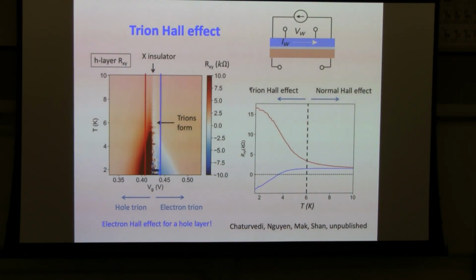Yeah. Trions are fermions. Yes. Unfortunately, the trions do not have high enough mobility for us to start seeing quantum oscillations at low enough magnetic field. At high field, there are other complications I would love to discuss with you. We think that when the cyclotron energy of the electron and the holes become comparable to the trion binding energy, it actually unbinds the trion. So we are limited by a very small window where the cyclotron energy has to be substantially smaller than the trion binding energy, and in that window we don't see quantum oscillation of the trions.